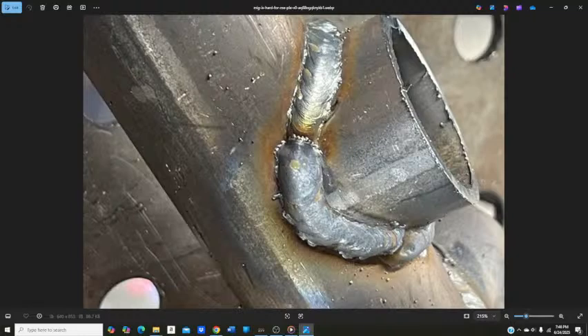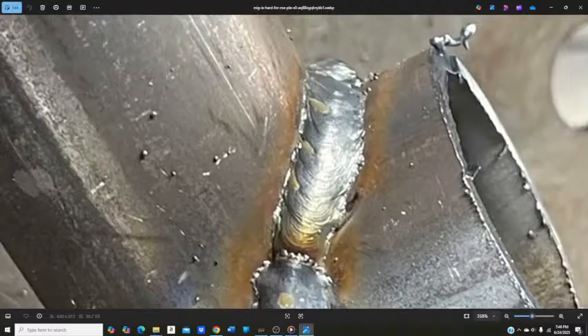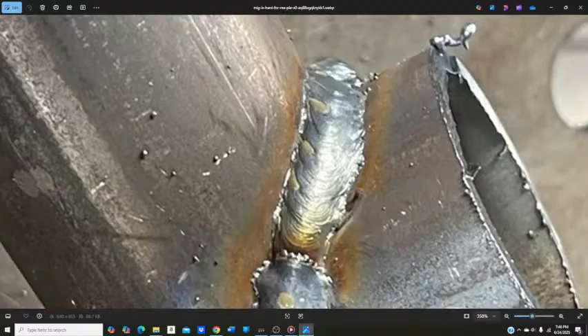You can see how the weld puddle is kind of melting into each piece of the metal as it was melting together. But you can notice the little, let me go a little closer here. You can see these little debris marks here, and that's actually contamination getting into the weld because it wasn't cleaned properly. So that's another issue with MIG welding. And then, of course, the spatter. You can see all the little BBs that are all over the place here. Those are all going to have to be knocked off or ground off to get the pipe cleaned up. So that's why MIG welding is a good welding practice for regular steel. But if you're getting into any of the exotic metals, stainless, chromoly, titanium, aluminum, TIG is a much better way of going. That's why, like I said, if you're going to buy a machine, a TIG machine is probably the best way to go.